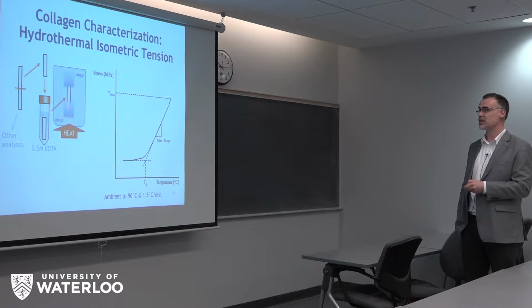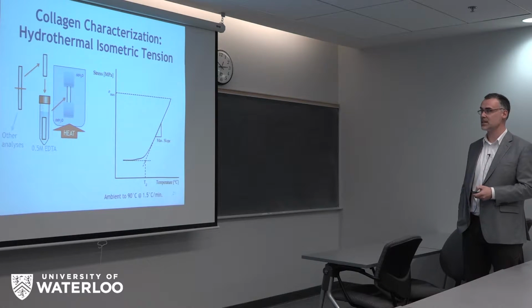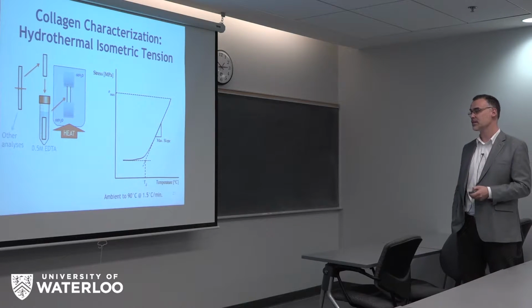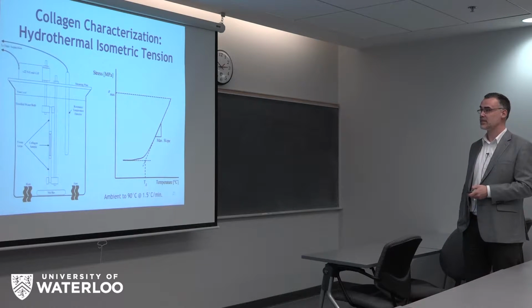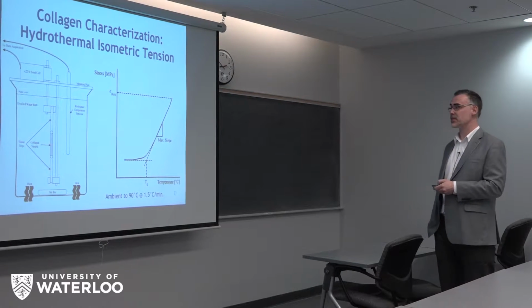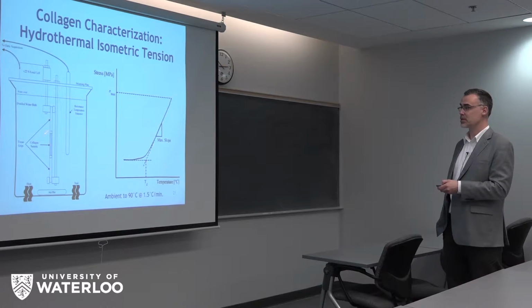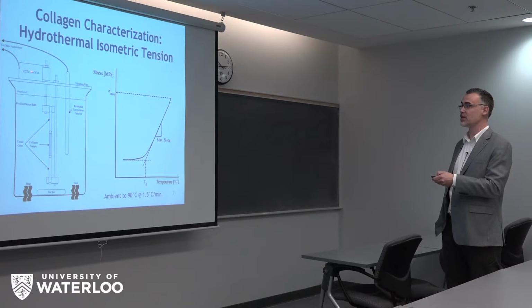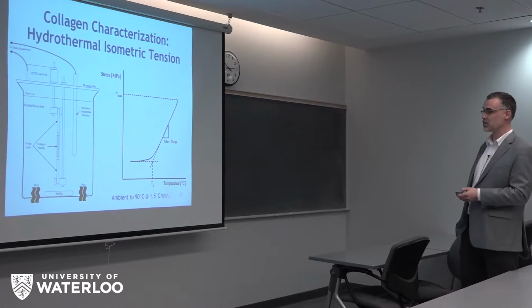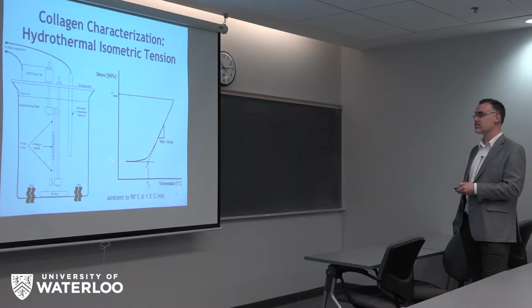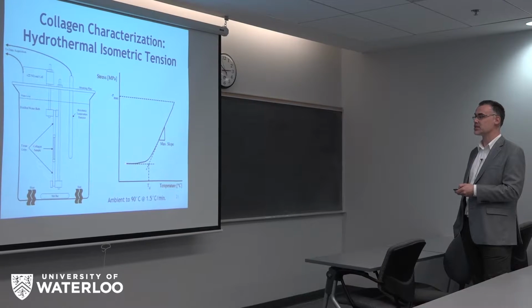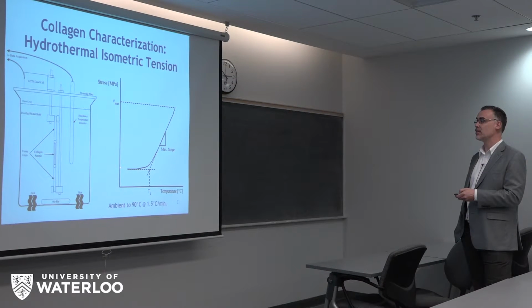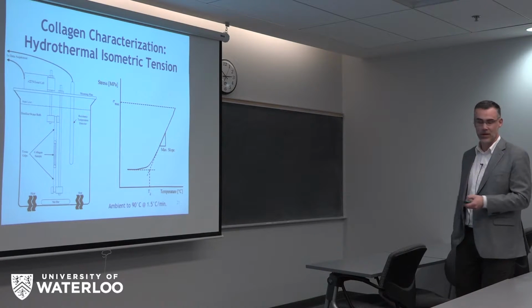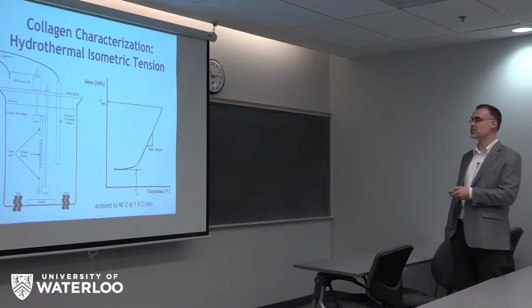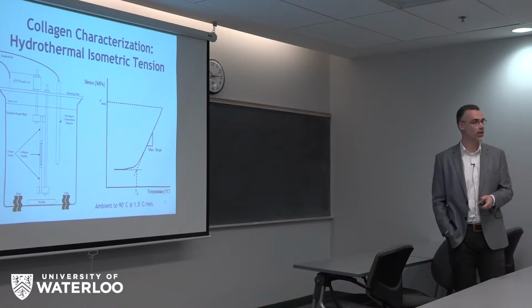So it's clamped between 2 clamps, and the water bath around it is heated up at a controlled rate from ambient to 90 degrees. And the device, this is a drawing of the device we've built. So we have our specimen between grips, some fixtures, and then a load cell, and it's temperature controlled. And so as we heat from ambient, which would be around 25 degrees, water coming out of the tap basically, it will eventually hit a temperature where the collagen is driven to melt, and that temperature will shift depending on degradation of the collagen structure.